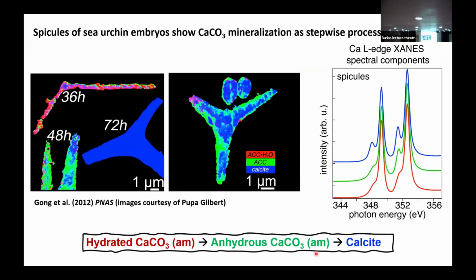Right, so this came out a little bit later, but I want you to see it because it's so fantastic. Gilbert imaged, using XANES, a very special method to work with these soft materials, the spicules of sea urchin embryos, and she showed their transient evolution as they form as embryos and then transform to calcite. And you can see these are color-coded by phase, where you go from a hydrated amorphous calcium carbonate, and here I'll just point here, hydrated amorphous calcium carbonate to an anhydrous form to calcite. And you can see from 36 to 48 to 72 hours, it's not just calcite, there was a pathway to the calcite.